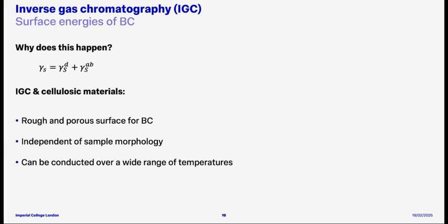And while contact angle measurements are typically used to determine the dispersive and specific components of a solid surface, this method is not very suitable for bacterial cellulose, as we couldn't produce a sample that is flat and non-porous. And here is where we collaborated with Surface Measurement Systems, and we use inverse gas chromatography, or IGC, to determine the surface energetics of this cellulosic material.